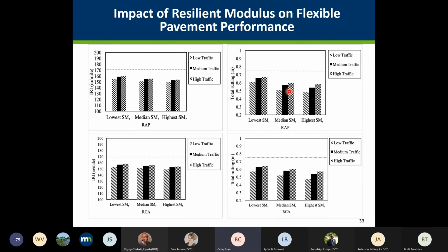And if you look at the total rutting, with both our RAP and RCA graphs on the right-hand side of the slide, the total rutting decreases with an increase in resilient modulus values of the materials. So this is as expected. And another thing that shows, even with the lowest resilient modulus values, when you use these RAPs and RCAs with the input parameters that we used for other structural layers of the pavements, they don't exceed the IRI limits. The dashed line here shows the IRI limits and total rutting limits. So these materials seem to be safe to use with these inputs in Pavement ME analysis.